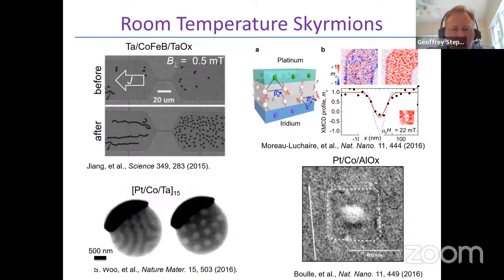So very rapidly after the discovery of interfacial DMI at room temperature in polycrystalline materials, a number of groups, including our own, were able to image circular structures that are topologically protected. So magnetic skyrmions that tended to be rather large, on the order of 100 nanometers or larger, in tailored multilayer materials. So things like platinum cobalt tantalum was a structure that we looked at. Iridium cobalt platinum is a structure another group has looked at.